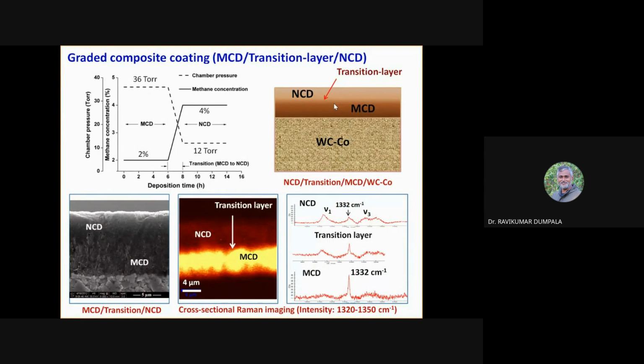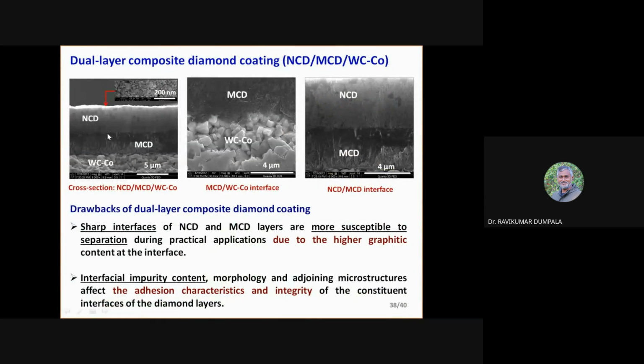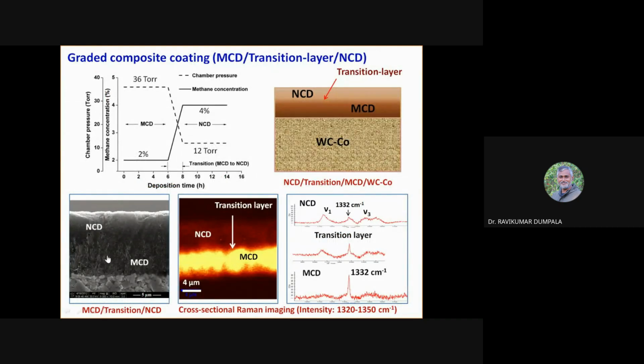In the previous figure, at the top left, you can see a clear-cut difference: NCD on top, MCD at the bottom. MCD means microcrystalline diamond, NCD means nanocrystalline diamond. You can see a clear difference in the top left figure. But in the bottom left figure, there are two layers, yet there is no distinguishable line between nanocrystalline diamond and microcrystalline diamond. That is because of the transition zone which we created by the process.